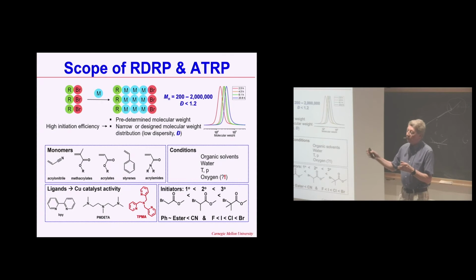Sometimes you want to have maybe a bimodal distribution. Some low molar mass can act as a plasticizer and some high molecular weight as a reinforcing material. So you can draw the molecular weight distribution. Sometimes for block copolymers, it can also give you access to new morphologies. Typically we take monomers which contain substituents that stabilize radicals. This would be a nitrile group for acrylonitrile, ester groups for methacrylates or acrylamides, but also benzylic structures.